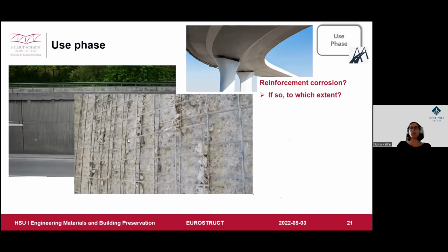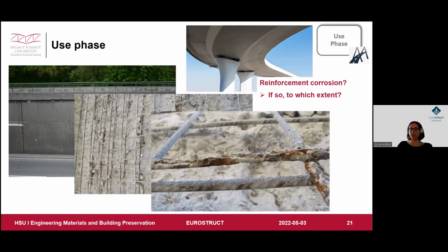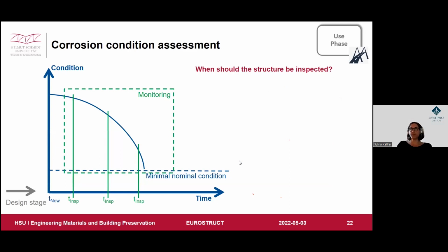And they ended up looking at the reinforcements. They had to do a total repair, because with a closer look during the repair, you see serious loss of cross-section due to corrosion. We had seen nothing from the outside. The abutment wall is more than 200 meters long on both sides of the street, and you have seen nothing. So what could we do, or what did we do during this inspection in order to check the corrosion probability?